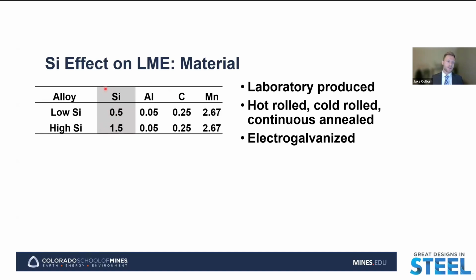The reason that we have the addition of silicon and also aluminum is that those can act as carbide suppression during the quenching and partitioning process, and also act as solid solution strengtheners. These two alloys were laboratory produced, hot rolled, cold rolled, and then went through continuous annealing simulations and were electrogalvanized with a pure zinc coating.